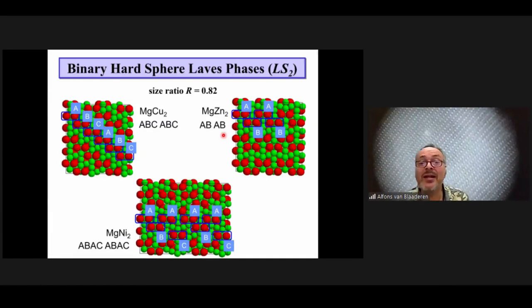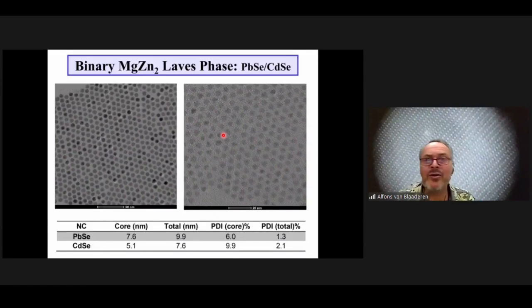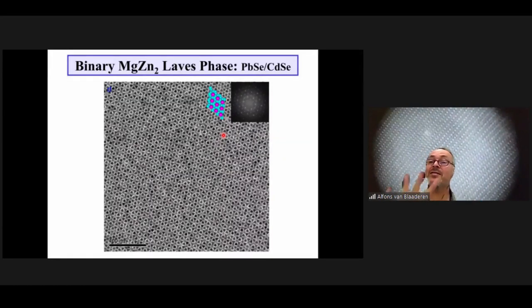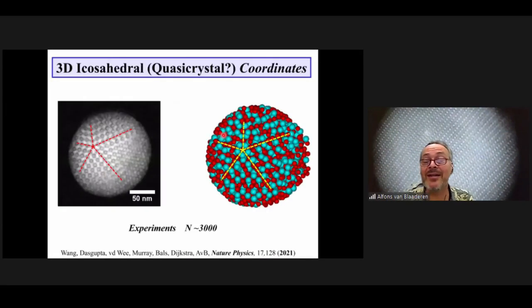So what we now found is that you can manipulate the self-assembly of these binary Laves phases by going to spherical confinement. So details are not so important. These are semiconductor particles, two different sizes. In the bulk, in one projection, you get this magnesium zinc 2 phase, what is expected. To be honest, you actually get a random stacking just like in hard spheres, but that is not how the nanoparticle people present their results. But if you have the stoichiometry exactly right, you get beautiful icosahedral structures with, again, the 5-fold symmetry, and that now have locally this magnesium copper 2 symmetry. So optically, very, very interesting.